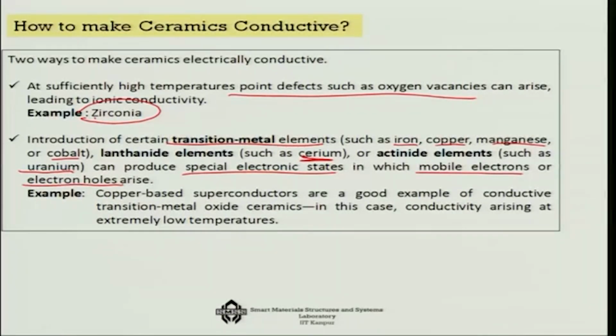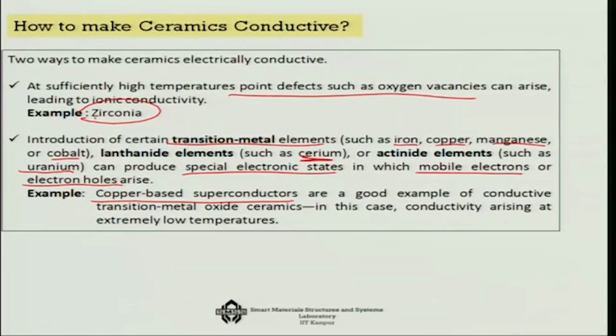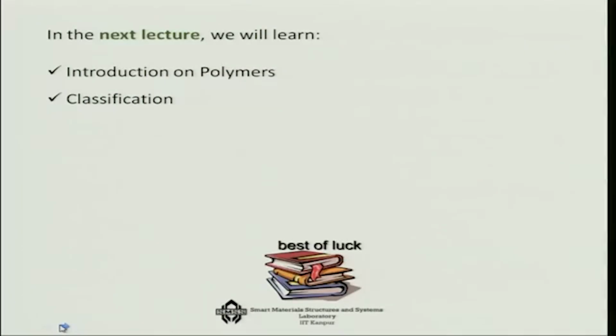Copper based superconductors are one of the best examples. Ceramics in general are not conductive, they are highly insulating, but the superconductors are made by using ceramics along with one of these transition metals, and then you increase the conductivity. Interestingly, this conductivity arises at extremely low temperature. So, on the one hand we have this high temperature raised conductivity, that is in zirconia, and on the other hand, this is extremely low temperature superconductivity, where you are adding transition metal elements to introduce conductivity into the ceramics. Of course, you can make ceramic composites to do a similar type of thing.